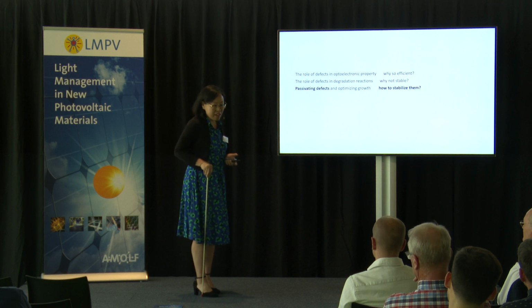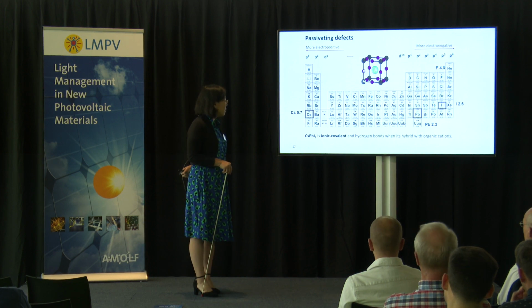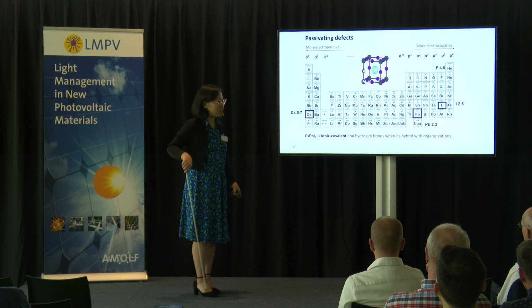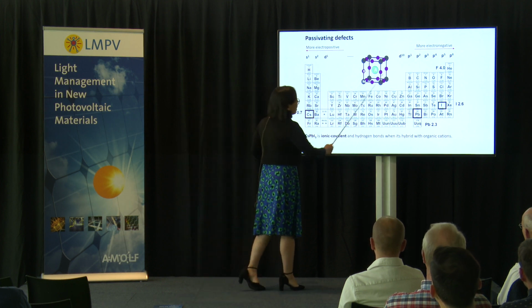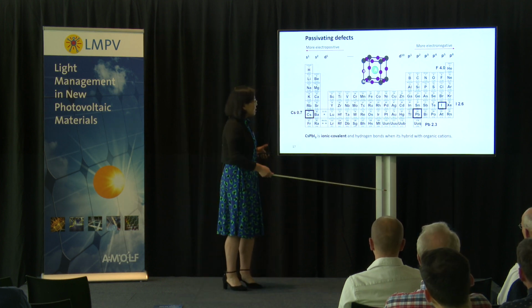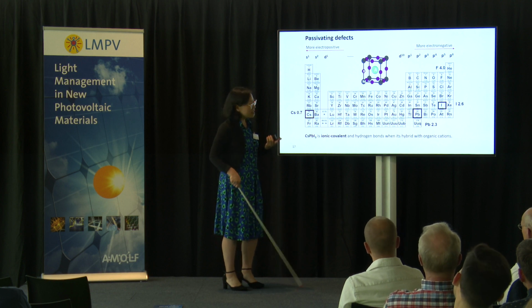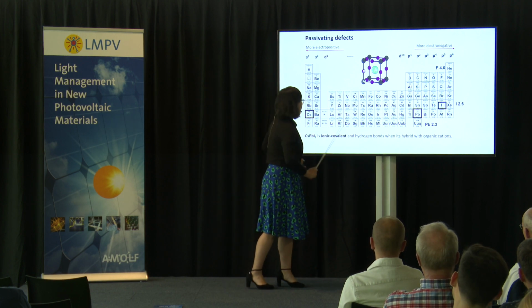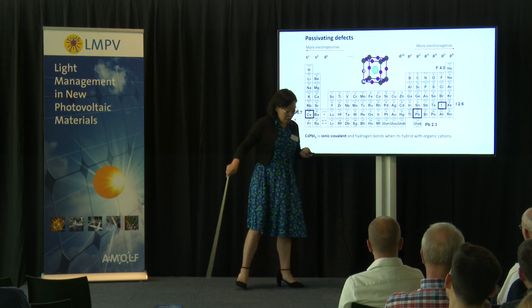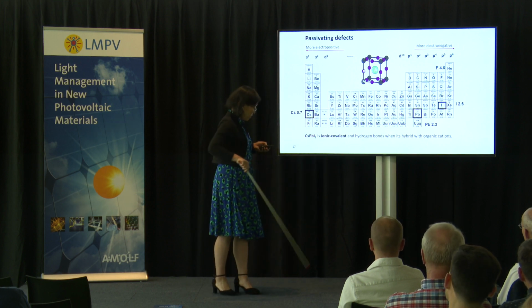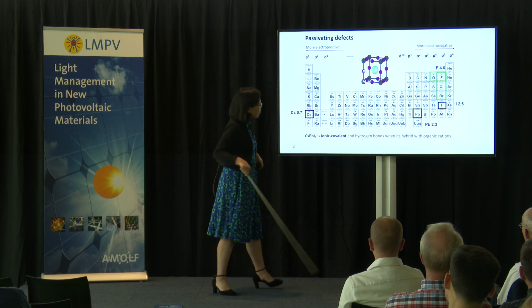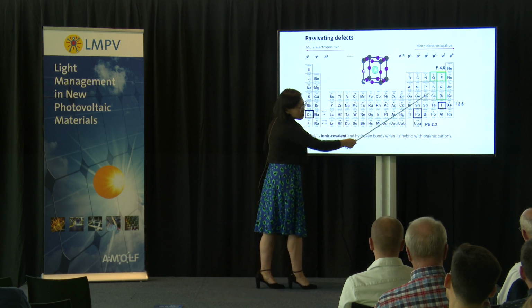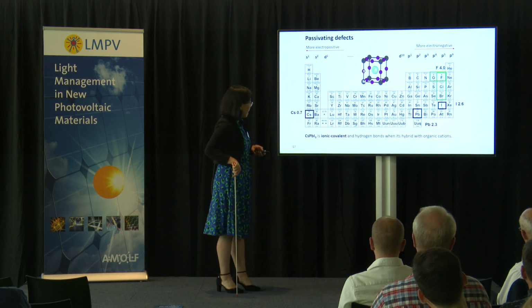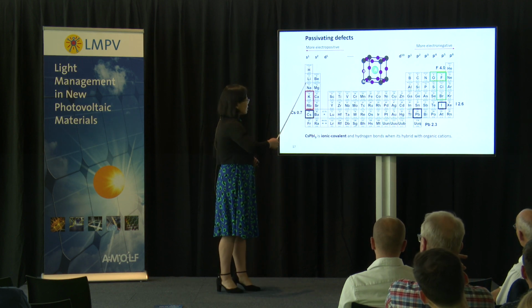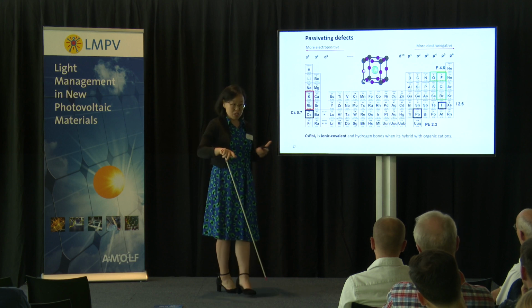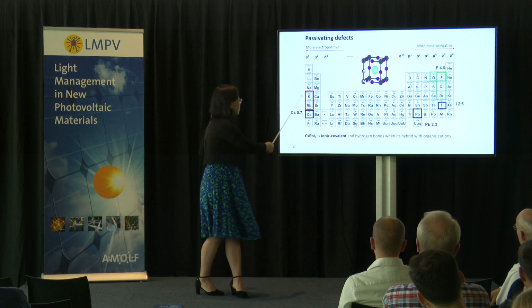So we're going to try to passivate them. In order to get very efficient passivation, we need to look at the chemistry a little bit. You see some lead iodide as an example again. So we need to find chemical species that form strong bonds with lead, but also with iodine. If you look at the other side of the periodic table, the species that can form strong bonds with lead are in this corner, and if you look at this side, the species that could go into the lattice and form a strong electrostatic interaction are on this side.